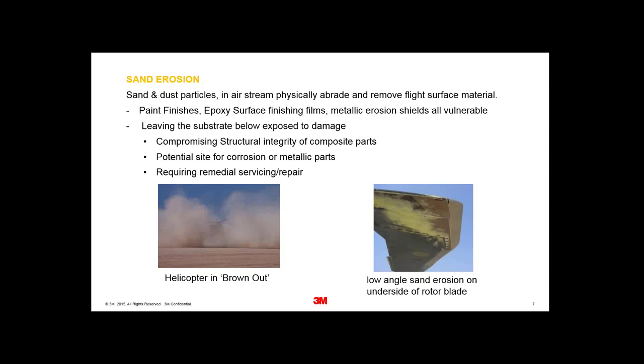You can see the sort of damage that occurs. This paint loss is not a long-term damage — the green top coat has been removed to reveal the yellow primer coat, and even that has been removed to reveal the bare composite underneath. That sort of damage occurs very rapidly, sometimes after only one or two sorties. Sand erosion is a very abrasive and very damaging type of erosion.